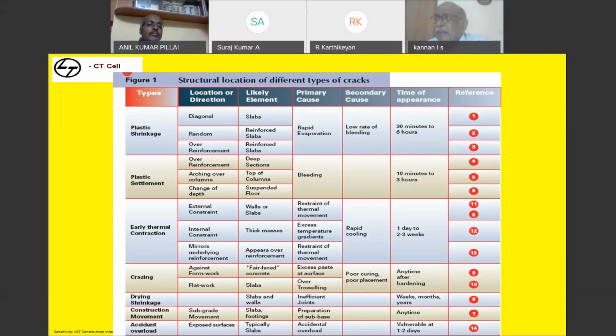These cracks can happen normally in the case of a slab or a foundation where excess compaction has happened and excess slurry accumulation can happen on the top. You can see some white patches on the top, then the white patches will slowly break. The breaking will happen like clay, how it breaks when the clay dries. It's all crazing cracks. Okay.